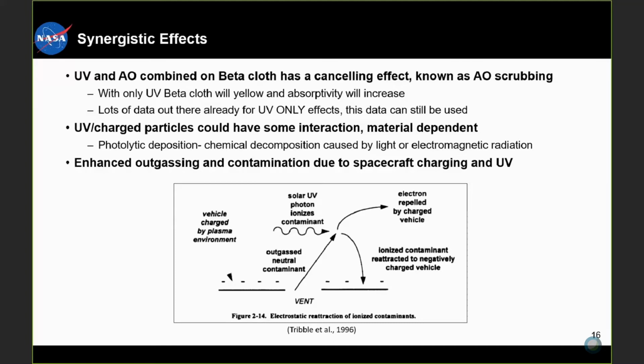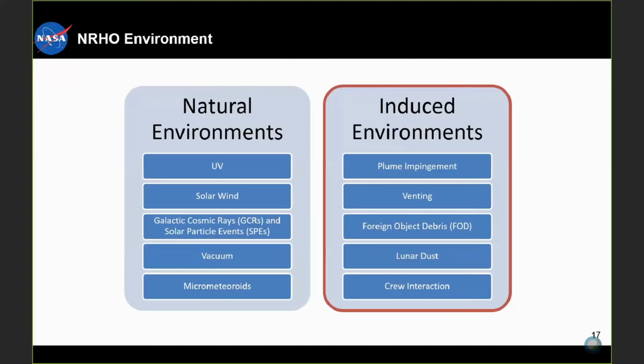So if you have a surface charge on your spacecraft due to the plasma environment, which we would have, this is like solar wind causes this. When you have outgassed products and they start to float away, then solar UV impacts them and causes them to ionize. So instead of being repelled by the charged vehicle, they could be reattracted instead, and then you have more contamination. So that's one way. There's also just the fact that the hotter the surface is, you could also just increase the amount that you're outgassing. So there's that.